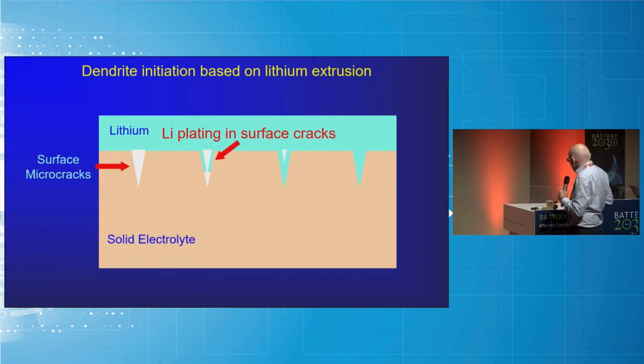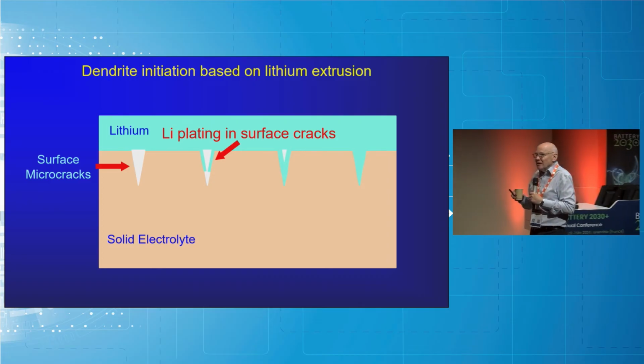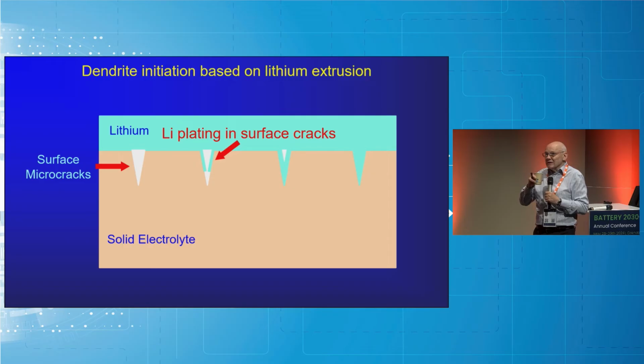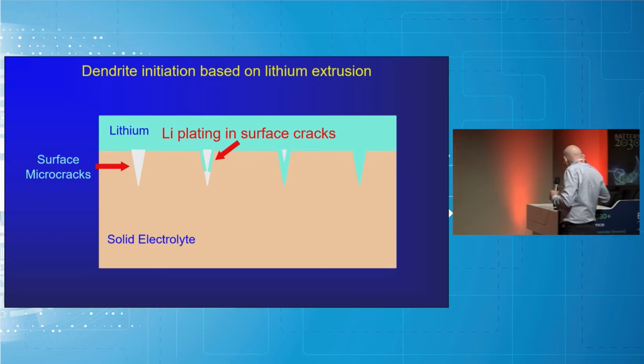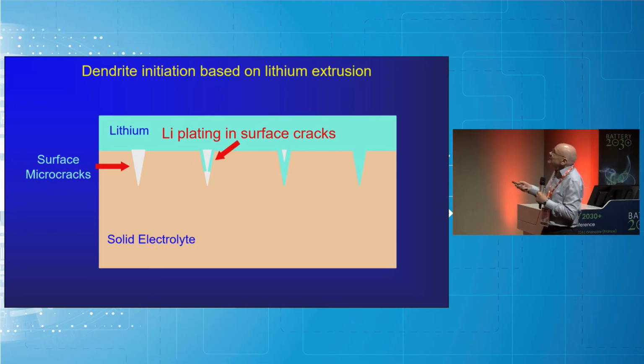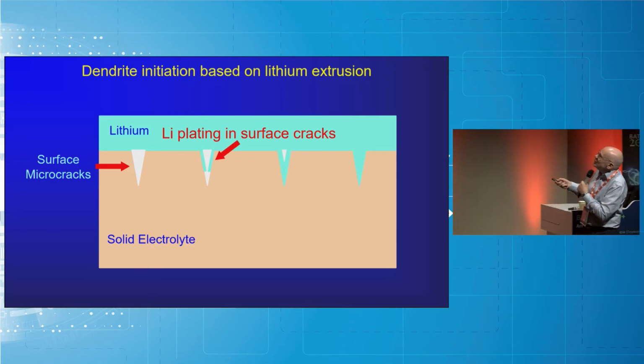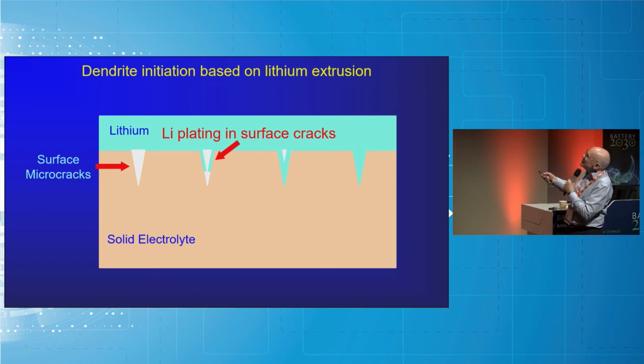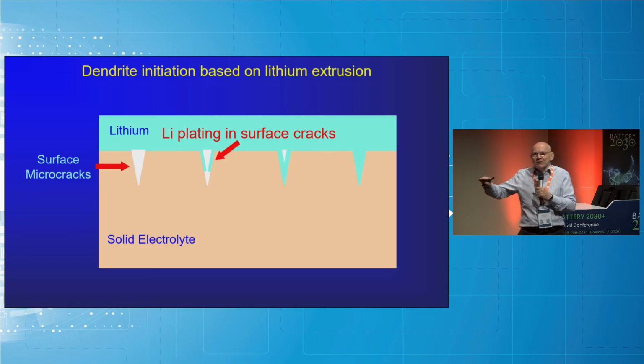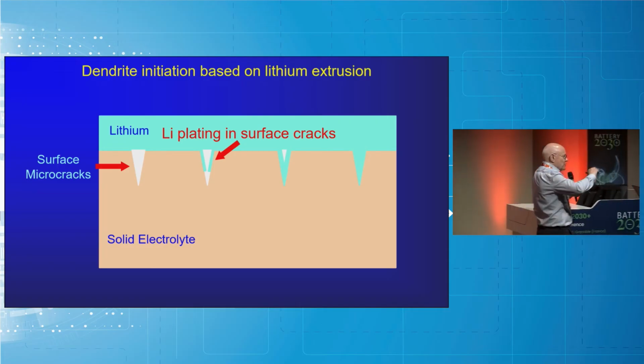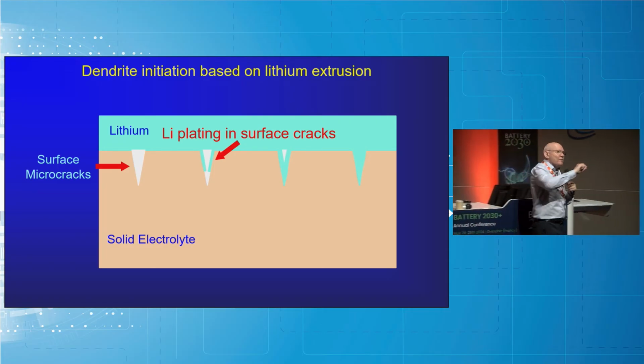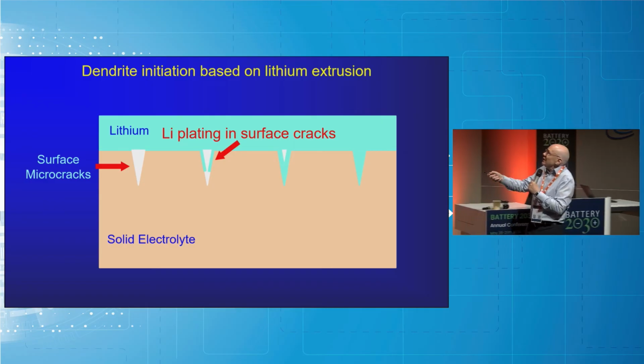So what I'm going to show you is our model of how dendrites initiate in a ceramic electrolyte when you try to plate a lithium metal electrode. First of all, here the solid electrolyte is in orange. The lithium is in this pale green. And any polycrystalline surface, even if you polish it, will have some crevices in it, some imperfections. And that's represented by these here.